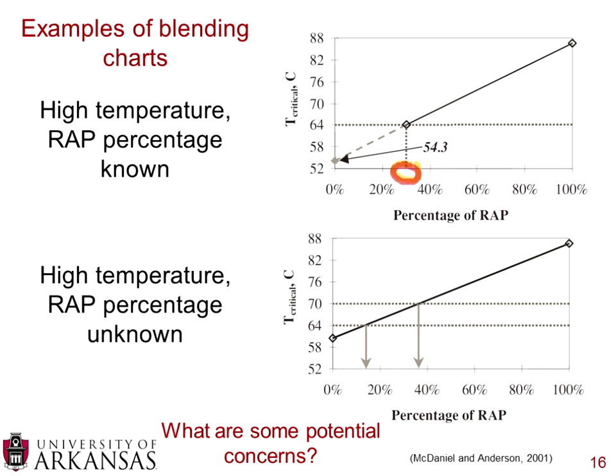You can go from the x-axis here up to whatever your critical temperature is right here, and then extract your line down here. And this is what your new high binder temperature is going to be. So if you're using approximately 30% RAP and you are using a PG 64 binder, you'll go down to the y-axis intercept, and you're going to end up with about a PG 54 binder for the high temperature grade.